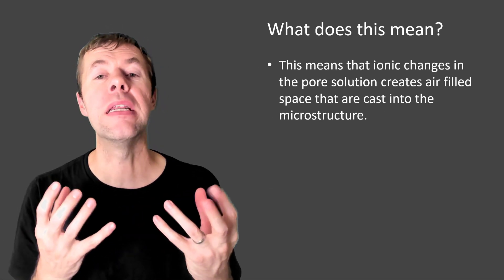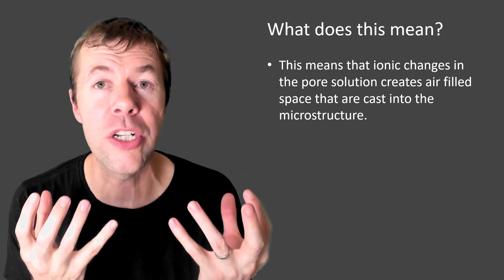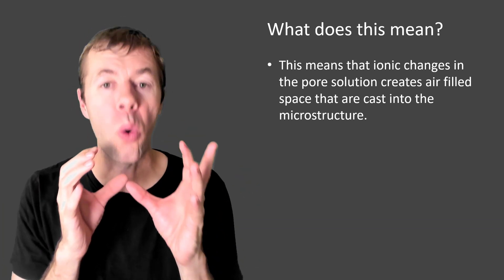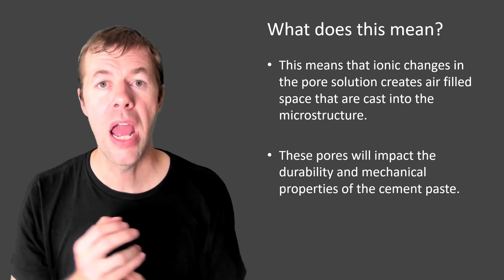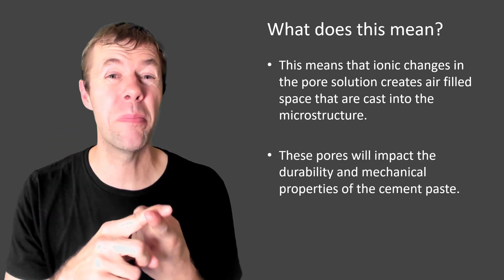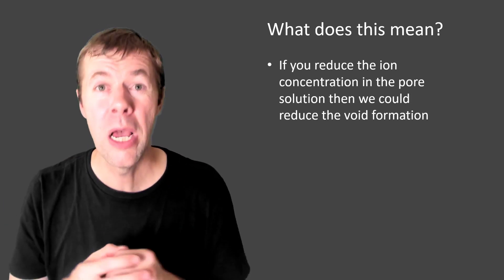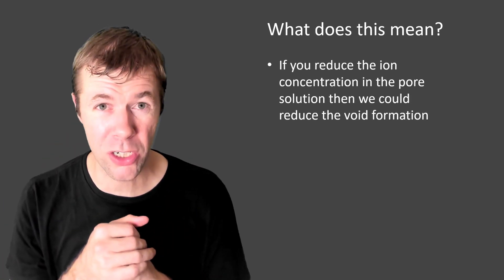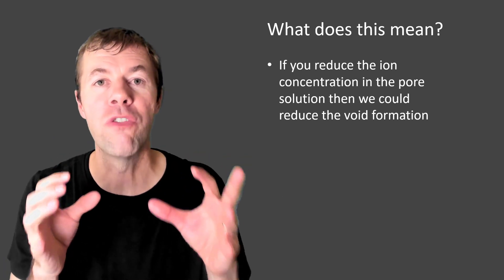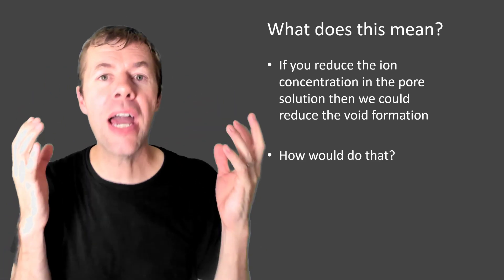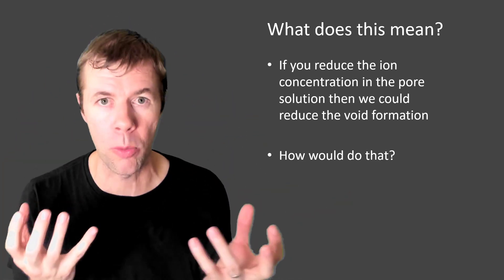So what does this mean? It means that the ionic strength, how much ions are dissolved in your water, is important. And it creates these air-filled spaces in our microstructure. And these pores will impact our durability, our strength, and lots of other properties about the paste. But if you reduce the ion concentration in the pore solution, then you could reduce the void formation. But how the heck would you do that? Well, you could use deionized water, but we wouldn't use that in normal concrete.